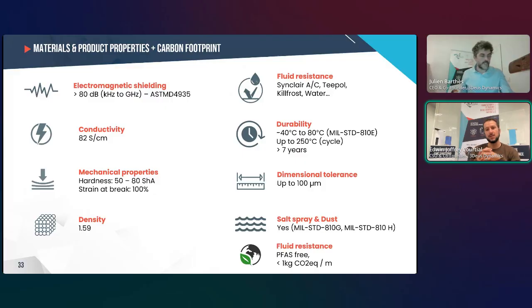Importantly, our formulation is PFAS free, aligning with the latest environmental and regulatory requirements in aerospace. And finally, the cherry on the top, the environmental impact of producing 1 meter of this gasket is extremely low, really equivalent to a single washing machine cycle. In other words, we have achieved the paradox of manufacturing a soft, high deformation PFAS-free gasket with metal-like shielding performance, all while keeping its environmental footprint minimal.